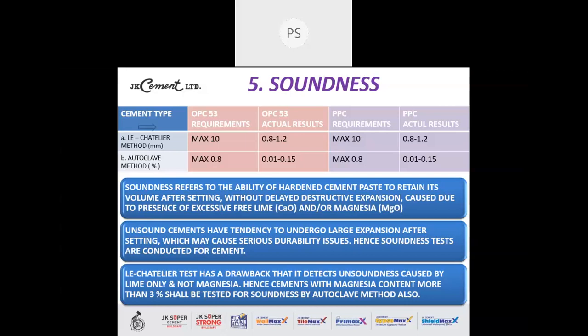If the cement is unsound, what will happen? The cement will start to expand. It will put a pressure on the nearest surface, that is the weakest surface, that is the tile, and the tile will crack. And in the worst case scenario, the cement and the tile will come out and fall on the ground from the wall. So this is the case. This is a very classic example and a very common problem that is faced with the unsound cements. If the cement is unsound, the tile will fall off. It will fall on the ground. So whenever you see such a case at your site, you can be sure that the cement is of unsound quality.